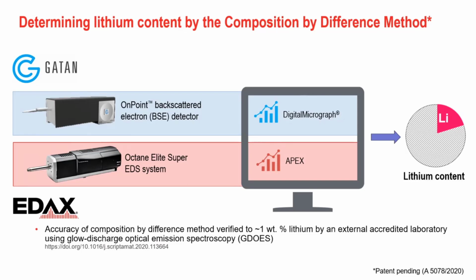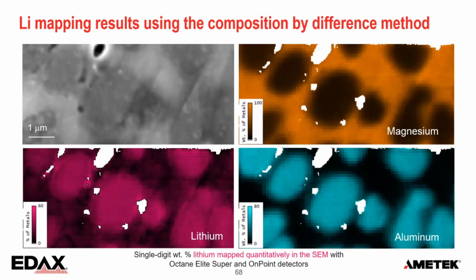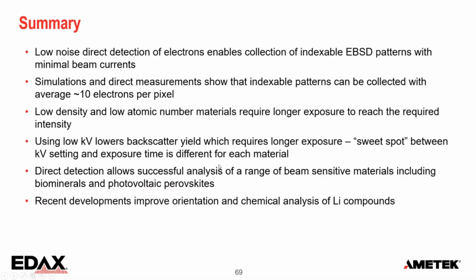And just to illustrate, here is a small map on this type of material where we just have the SEM image, magnesium, aluminium, and here on the lower left is the lithium map, where we can quantify from zero up to about 60% in a beautiful mapping. So we don't need half of the material to contain lithium. So that is something I just wanted to quickly present to you.